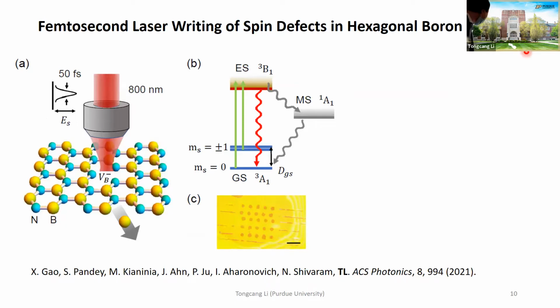So we first use femtosecond laser writing. We just use an 800 nanometer femtosecond laser and pass it through the hBN flake, and there we create vacancies. We found that we can create this spin defect with quite good, reasonable contrast. After laser writing, it will naturally become a charged defect, or you apply some gating to transfer from the neutral defect to the charged defect. So what we believe is that when we use femtosecond laser writing, we create both the negatively charged and the neutral ones. We didn't do any extra control.